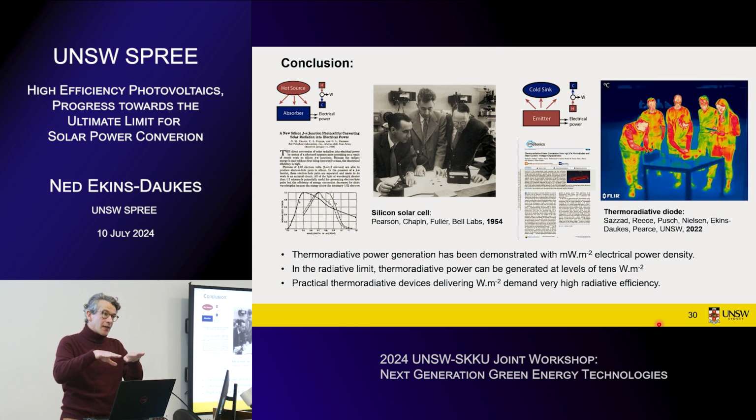So then you say, okay, the only thing I can do is either increase the excited state lifetime. So you mentioned using rare earth ions, and they have very long lifetimes. The only problem with rare earth ions is the optical transitions are forbidden, so then they're weak. So that means they don't absorb very well. So then the challenge, which I think you've alluded to, is that you want to try to sensitize those ions so that they can absorb more strongly. And that is one of the possible pathways you might be able to solve this problem.